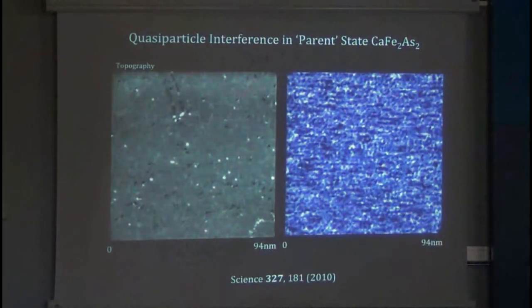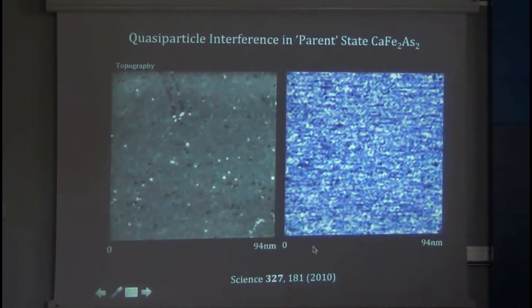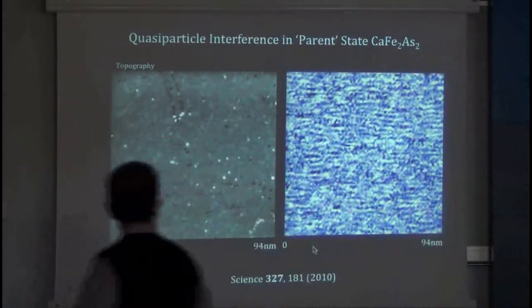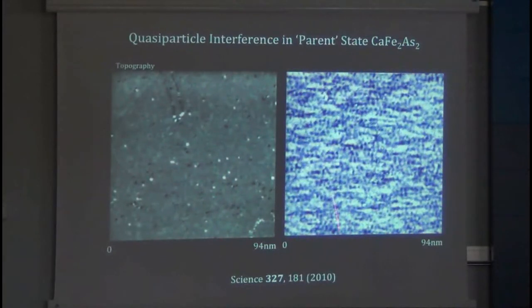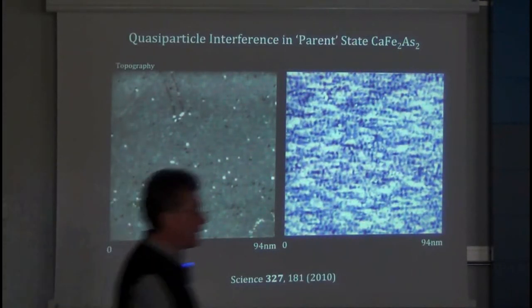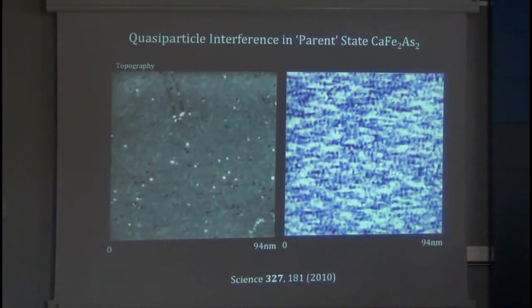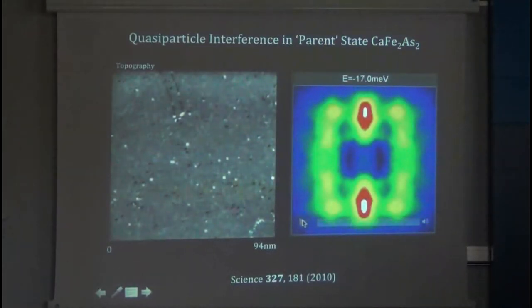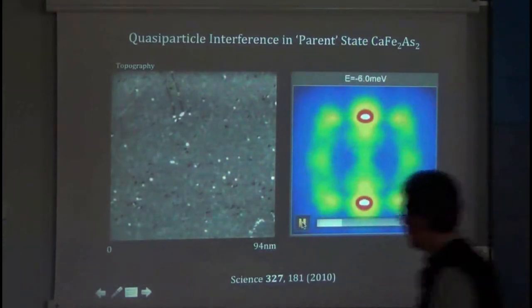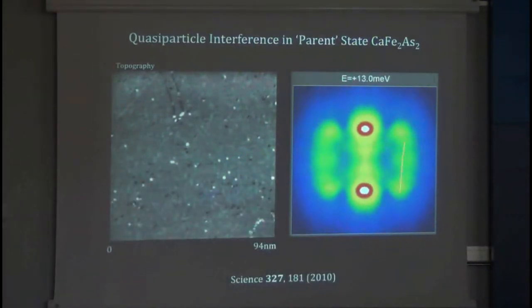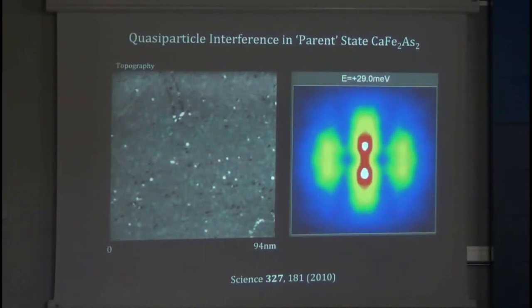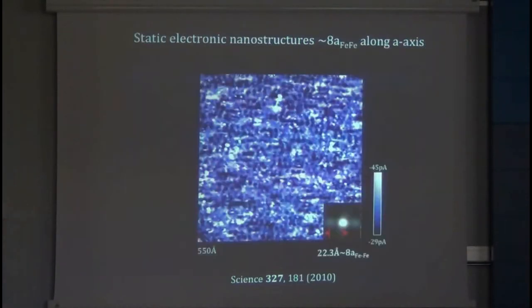Okay, so we understand this surface very well, and on that surface, we were able to take the first wave function images of the pnictide compounds. We did this in the middle of 2009, and we found that the states, the parent states, were very strange. The de Broglie waves are only dispersing along one direction here. And if I show you the Fourier transform, it's easier to see how strange they are. Here's the Fourier transform of that data. The wave vectors are all dispersing along one axis, but not along the other axis. The delocalized states are all propagating in one direction, but not in the other direction.